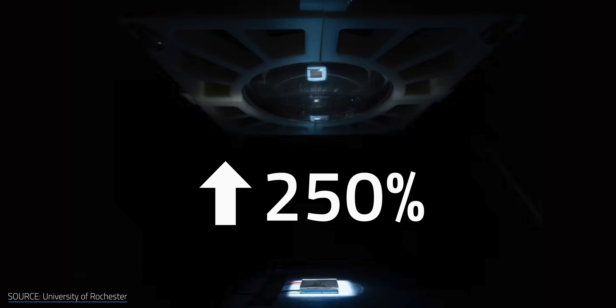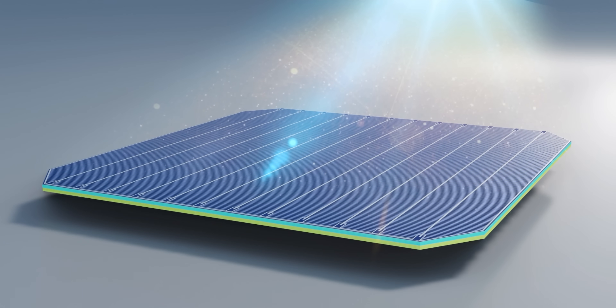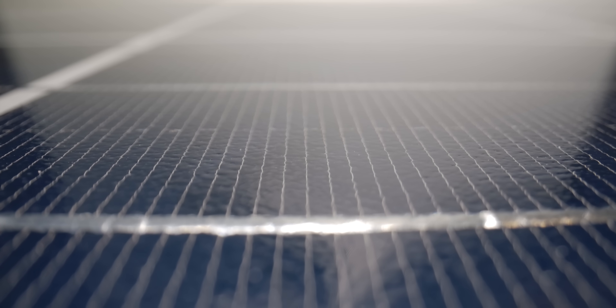This mirroring effect ended up increasing performance by 250%. Before we get too hyped up, let's clarify that this isn't a direct 250% jump in power conversion efficiency — the percentage of solar energy converted into usable electricity. We're actually talking about how long the electrons bounce around inside the cell before they dissipate, or the carrier diffusion length. That's where the 250% jump is happening. Just because we vastly increase photosensitivity doesn't mean we vastly increase the final power output. However, this is still a very noteworthy development because it opens the door for far more advanced perovskite cells.